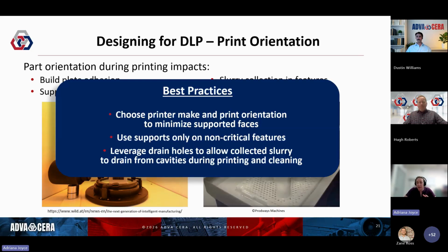Sometimes that print orientation might mean the print takes a little bit longer because it has to be printed in a vertical instead of horizontal orientation. But because the cleaning and thermal processing, as well as the post-processing, cleaning up any residual from supports, are all simplified, the final part actually ends up being less expensive and much higher quality.